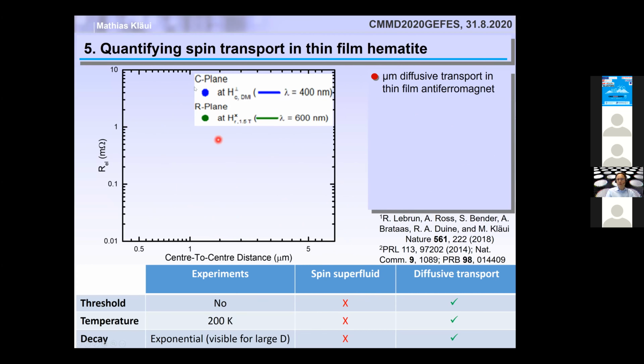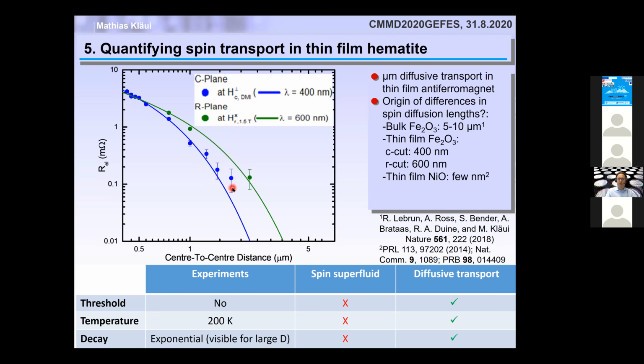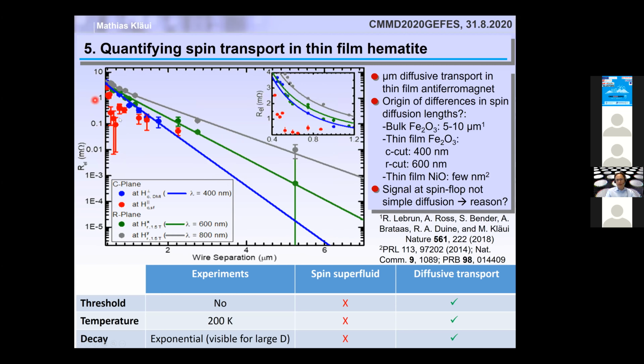and we found that, for instance, on C-plane, we have a spin transport that occurs over something like 400 nanometers. On R-plane, we see transport over about 600 nanometers, and then depending on the applied field, we even have the situation where we cannot fit the decay by a single exponential. So it's not purely diffusive transport. And the question is, where do all these differences come from? Because fundamentally it's all the same hematite.